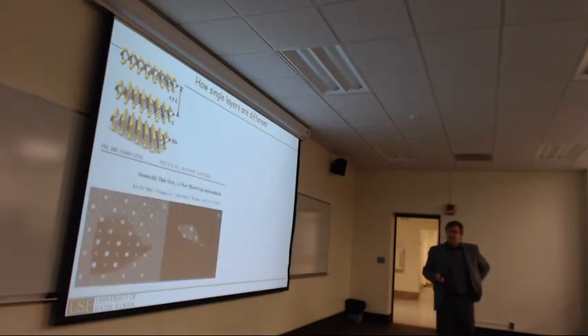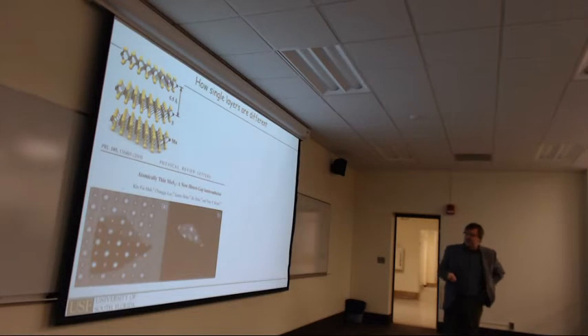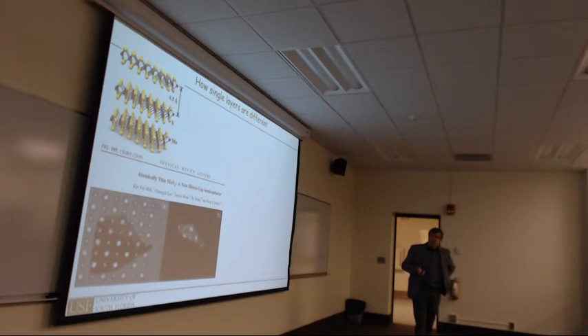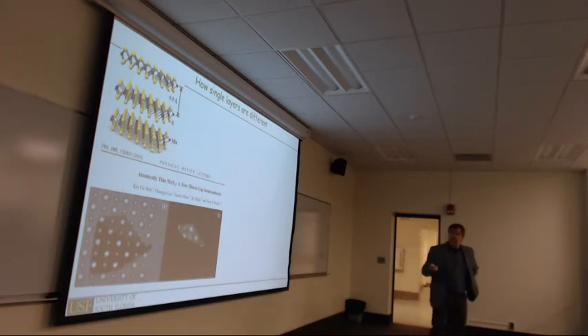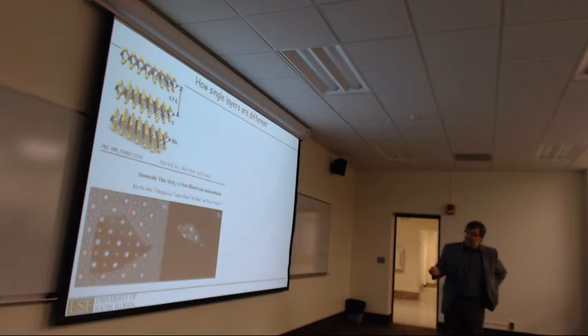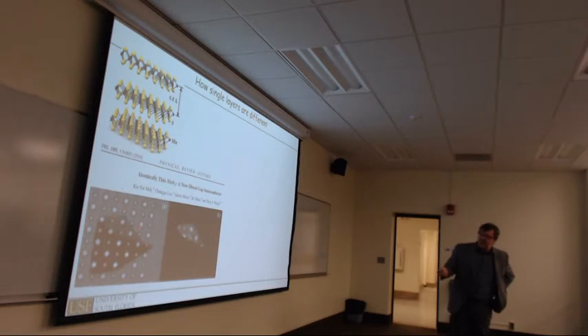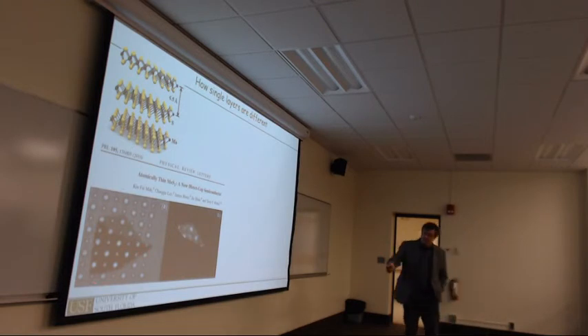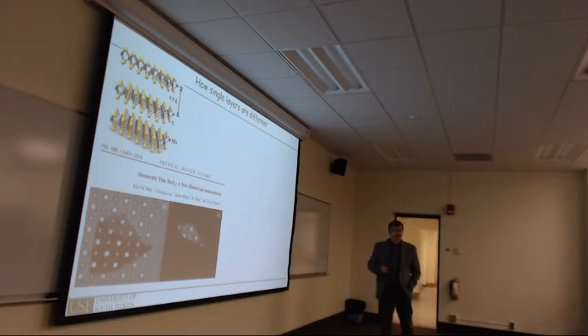And I guess the nicest example is this paper, which is already almost 10 years old, where they looked at molybdenum disulfide and exfoliated it with the scotch tape method. And so you get little flakes, and this is a flake of molybdenum sulfide, put on a TEM grid, so the holes are just holes in the transmission electron microscopy grid, and this is the flake. So there's just an optical microscope. You can see a darker region, which is bilayer, and a less dark region, which is monolayer of the same flake.